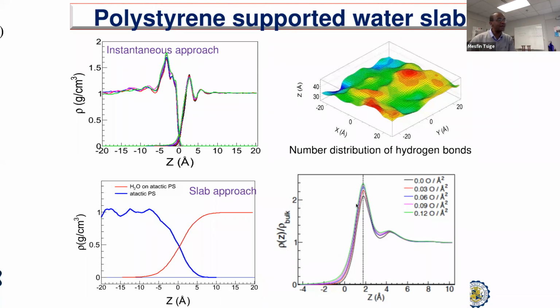In our case, we don't see that too. At 0%, our surface is hydrophobic, and we pretty much see a high density of water nearby with no depletion compared to the oxidized surface. So this is 0%. This is as we increase the hydrophilicity, so less contact angle. Yes, we have higher density. More and more water molecules are adsorbing on the surface, but we didn't observe any depletion region. And beyond 6 angstrom, we pretty much recover the bulk properties of water, which means the interface is actually affecting about 6 angstrom of water molecules from the interface. So we identify those water molecules within 6 angstrom as interfacial water molecules.